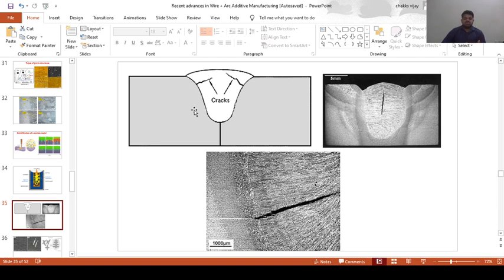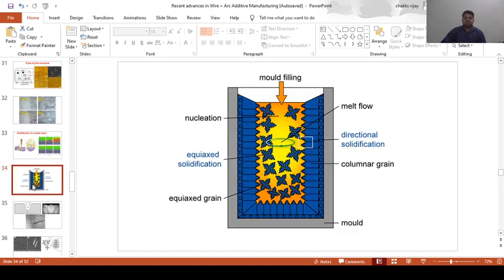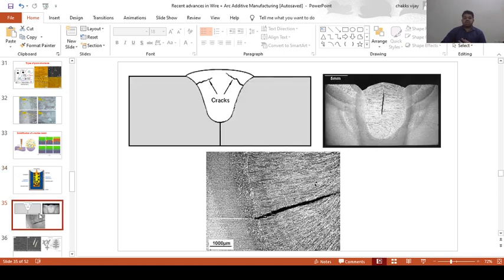ER represents the electrode wire, and 4043 is the aluminium 4043 series, which is called a universal filler wire. For welding any grade of aluminium, we generally go for ER4043 because it has an aluminium silicon combination, which will improve the surface wettability. So the interdendritic liquid will be very high, so it can potentially heal all the cracks and voids. If your material has insufficient interdendritic liquid, in this orange zone, then obviously it may lead to cracking formation.